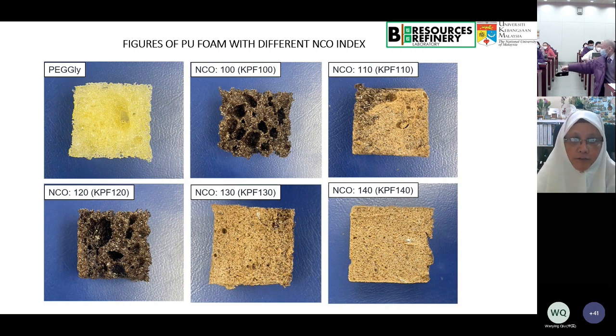So this is the example of PU that we made in the lab. It's a very dark color because of the lignin itself. And this is from KPF, without just polyethylene glycol. This is KPF at different isocyanate levels. So it gives you different foam sizes and pore sizes. But we are interested in the 100. Although the strength is not good, as far as an agriculture pot is concerned, this is the best. So we tend to make it into a pot.